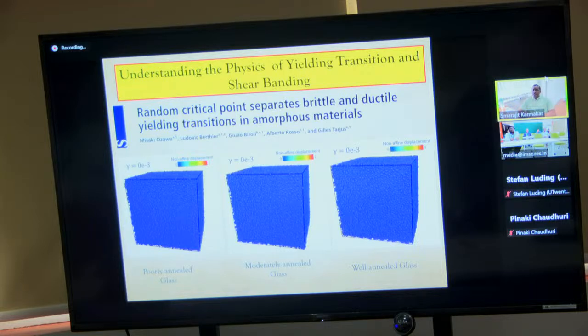So they took polydisperse systems where you have a continuous size distribution, and then they tuned various parameters, including the distribution, the shape of the distribution itself, and were able to tune the swap efficiency to a scale which is remarkable. And some of their papers, at least this paper published in PNAS, reported a speed up on the order of 10 to the 6.